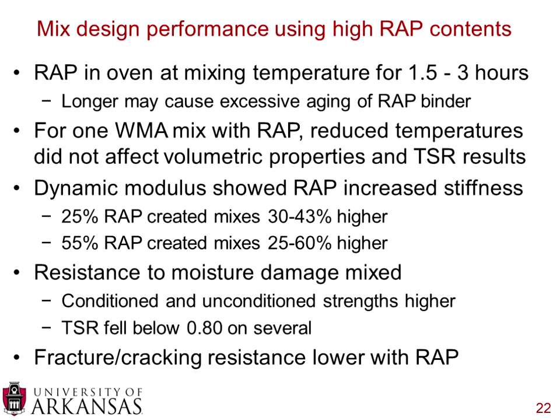They did find that adding RAP increased stiffness according to dynamic modulus. By adding 25% RAP, the dynamic modulus was anywhere from 30 to 43% higher. And by adding 55% RAP, it was 25 to 60% higher.